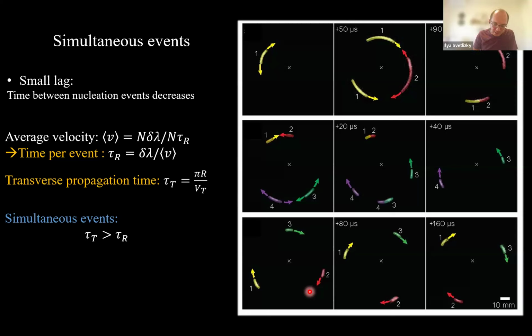And for some time, we thought this is intimately related to Jay's crack front work. Jay and others have worked on crack front waves, where the waves have some out-of-plane contribution, which leave a mark in the plane. I think it might be similar. Maybe this is the mechanism that makes the difference between the KC for nucleation and KC for arrest. So the crack surface is not flat, it leaves clean signatures, but we were not able yet to make science out of that. Yeah, that's cool.